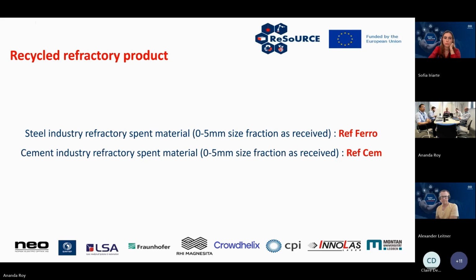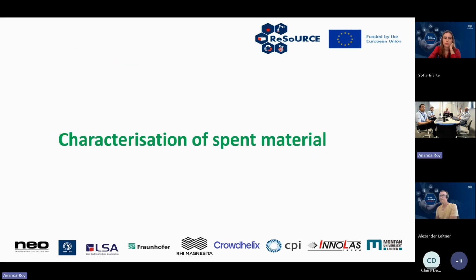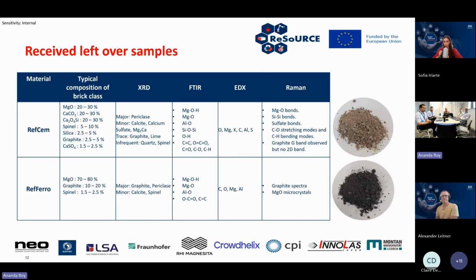So, as Ananda mentioned, these materials are spent refractory materials. And so the first thing that we decided to do was undertake a characterization of what these materials are and how they behave. So we started by looking at the chemical composition of these materials. And we used a range of the different techniques that we have, looking at XRD, FTIR, EDX, and Raman, where we can really look at what phases are present, what bonds are present, and what elements are present in these materials.